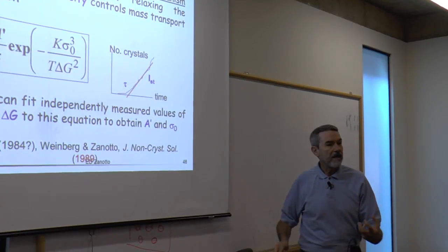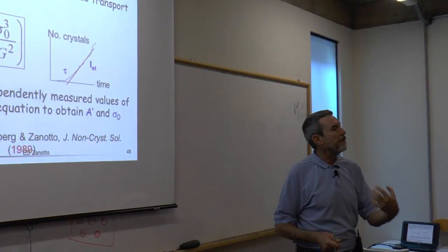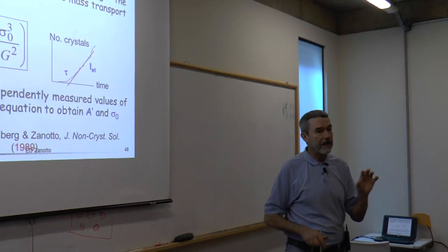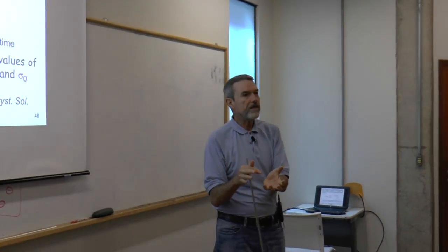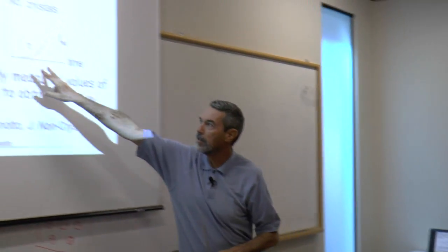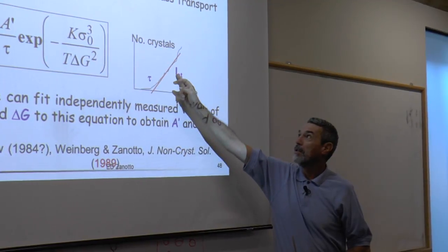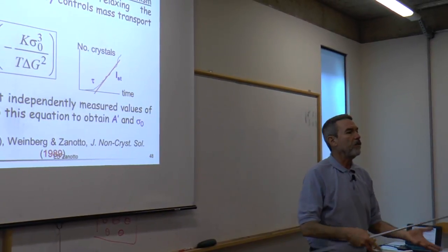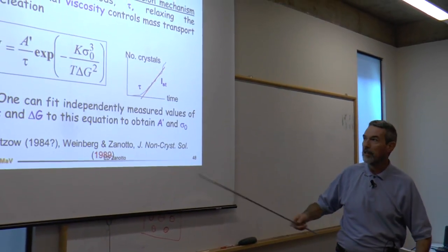And these induction times are also related to some kind of diffusion coefficient. We don't know exactly which are the diffusing units, but there is some diffusion unit controlling these times, which should be the same that controls the steady state nucleation rates. Everything is the same nucleation process. So we can rewrite the expression.